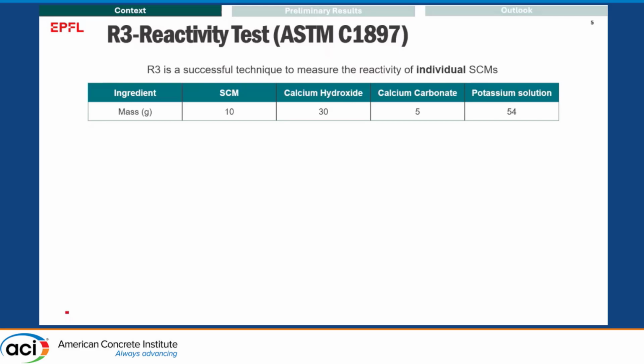There are a variety of reactivity tests in the past, but recently many of them reached consensus about the R3-Reactivity test being one of the efficient methods to understand the intrinsic reactivity of an individual SCM. So what we do in short, in the R3-Reactivity test, is we have an SCM, we let it hydrate in the presence of excess calcium hydroxide, as you can see here. These are the mixed proportions, by the way. In excess calcium hydroxide, also in the presence of carbonates, alkalis, and sulfates, a system similar to cementitious system.